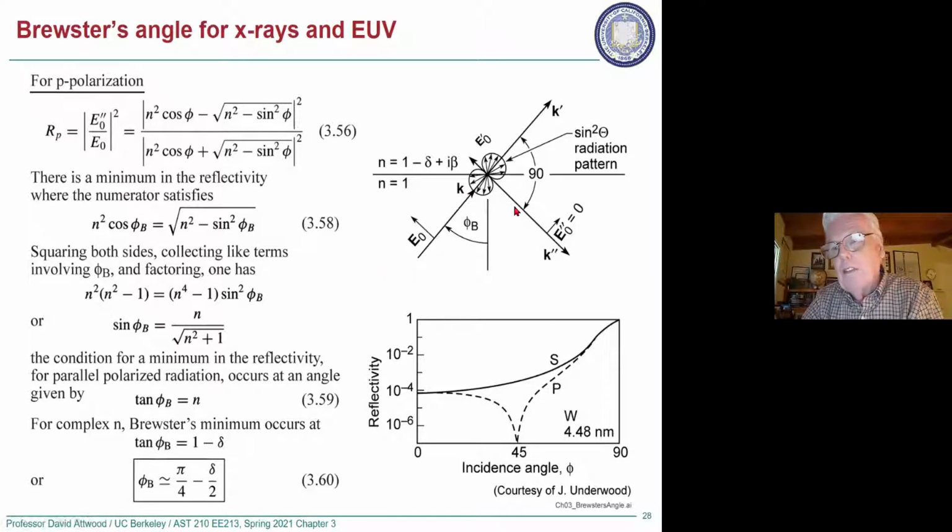Yeah, by the way, someone who's interested in magnetic fields, and you want to see a rotation, you want to see how some electromagnetic wave that's probing cobalt or iron or something else rotates, you need a polarimeter, something that can measure polarization and rotation. One of the ways to do that is to use Brewster's angle. So have two mirrors and maybe have one of them rotating in such a way that it always nulls out the field, okay? And you just track it. After going through the magnetic material, there's a Faraday rotation of the polarization of the electric field, and you can use this effect to track it. So it's a method used for measuring Faraday rotation and therefore magnetic field strength in magnetic materials.